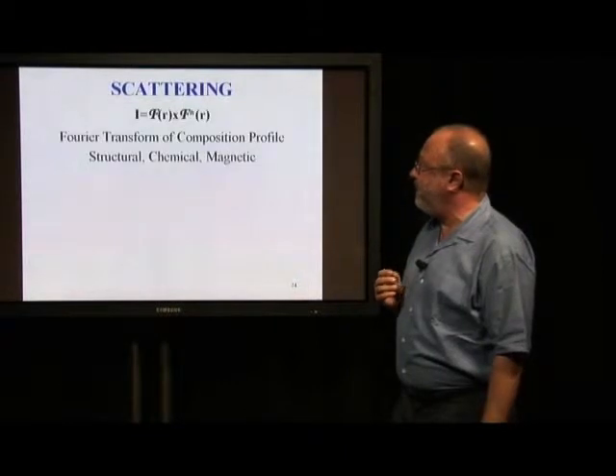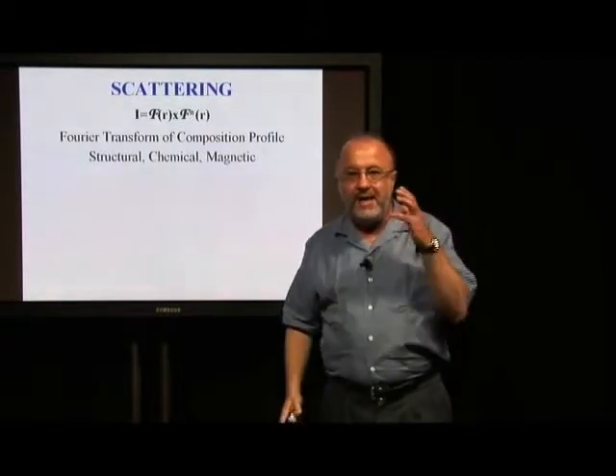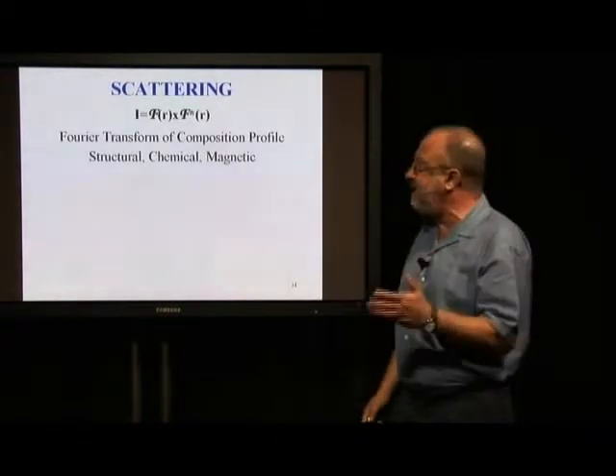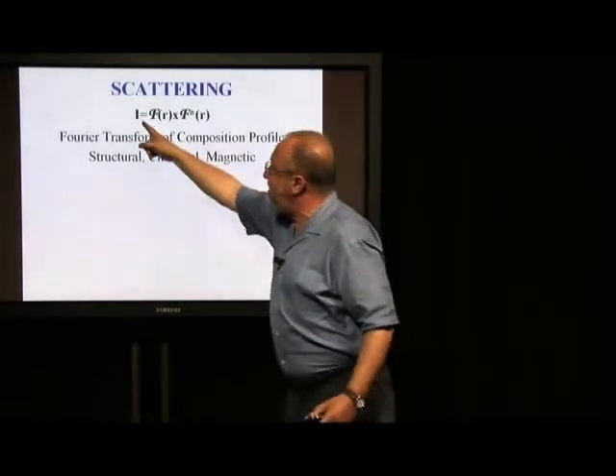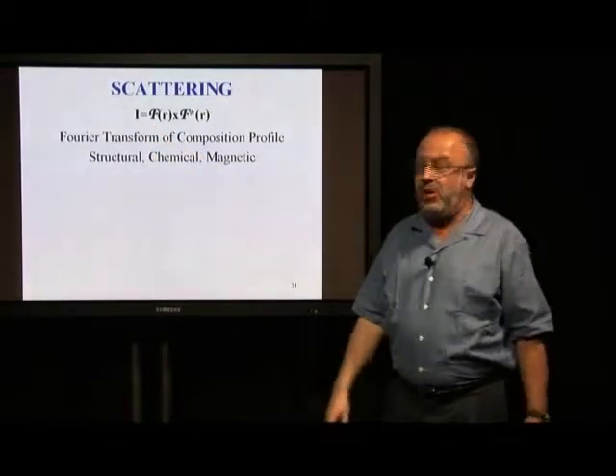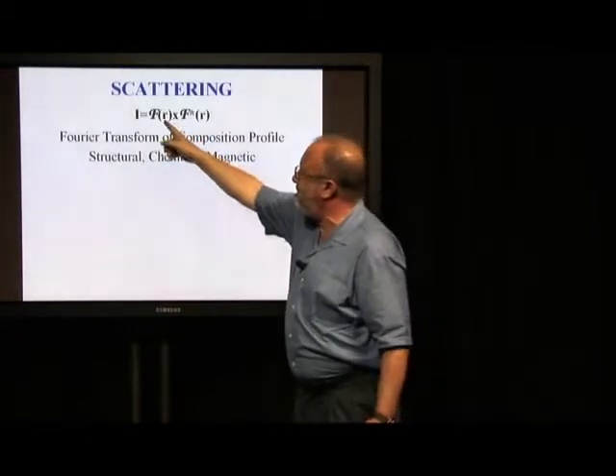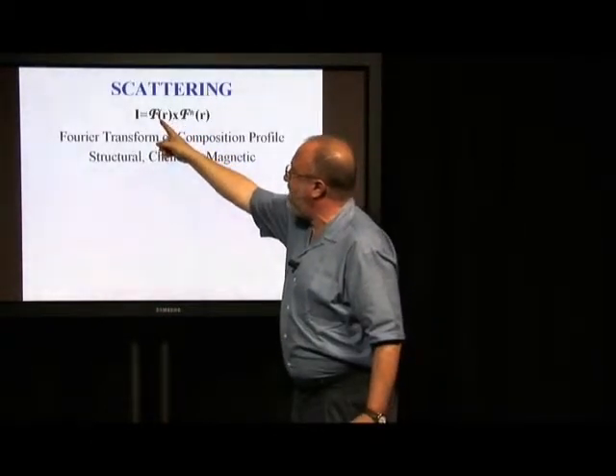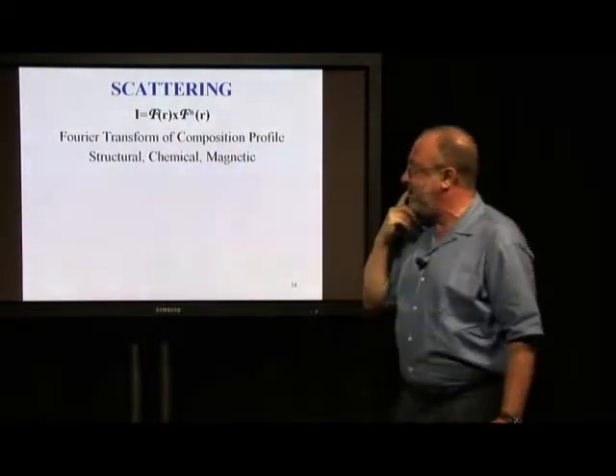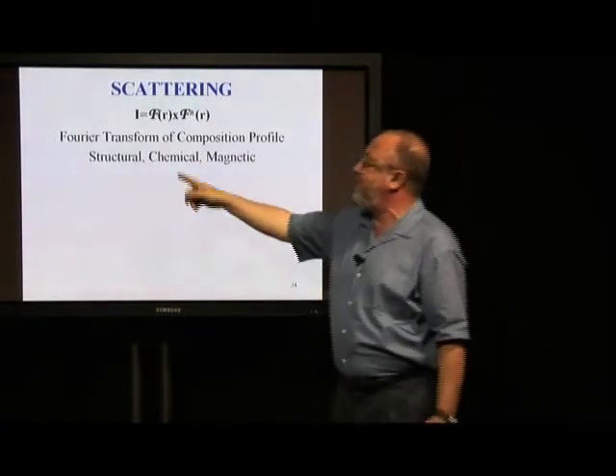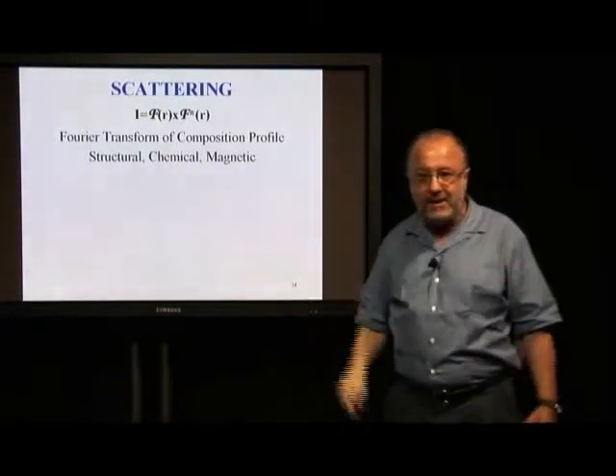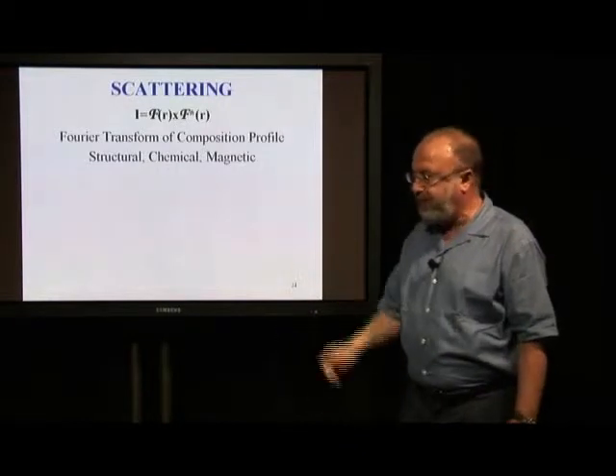And what I want to show you here is that you have to remember that X-ray scattering measures the intensity of the X-rays, which is no more than the square of the structure factor. So it's the product of the structure factor times its complex conjugate. And this actually gives you information about structural, chemical, and magnetic properties of the interface there.